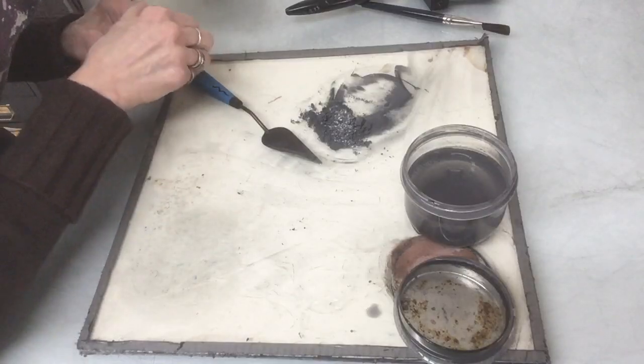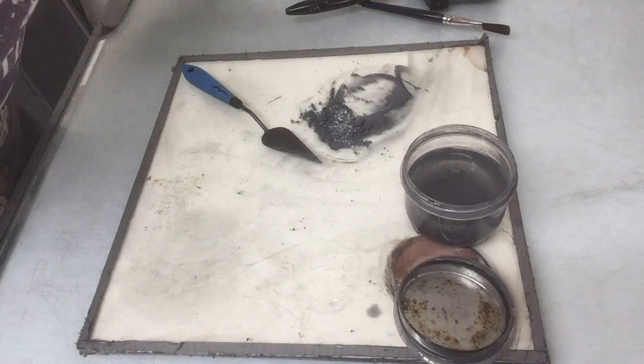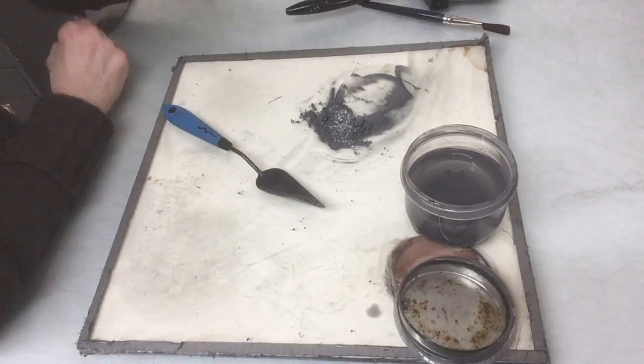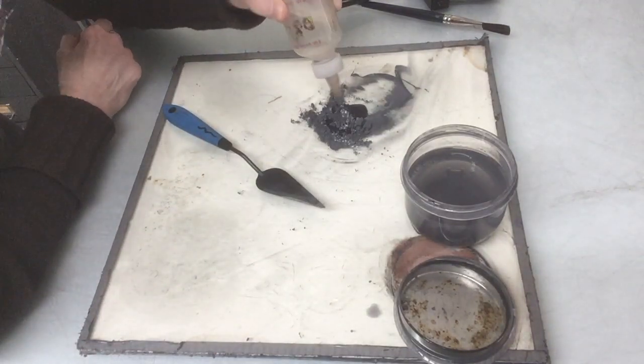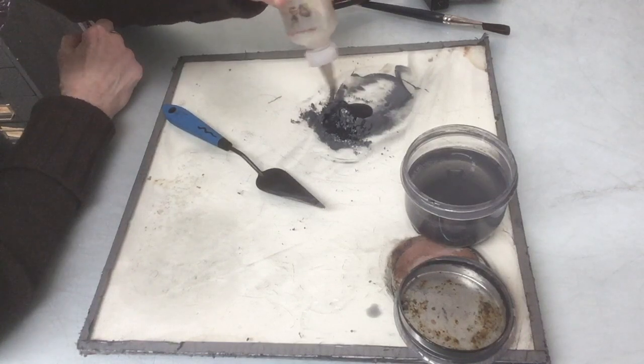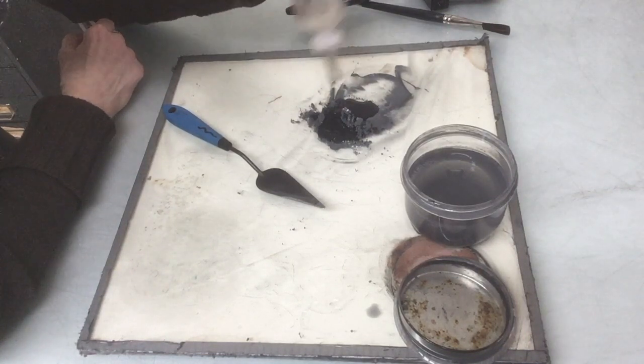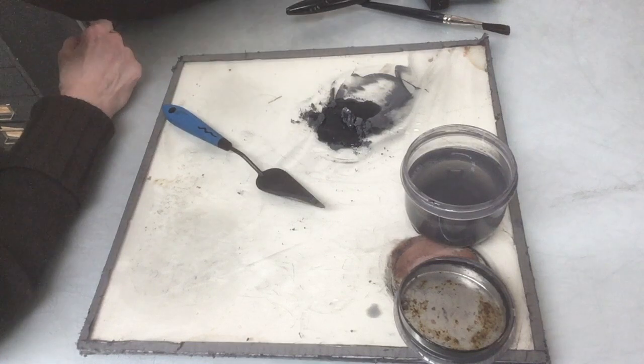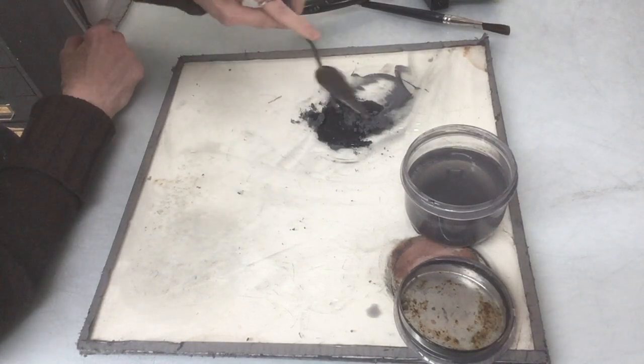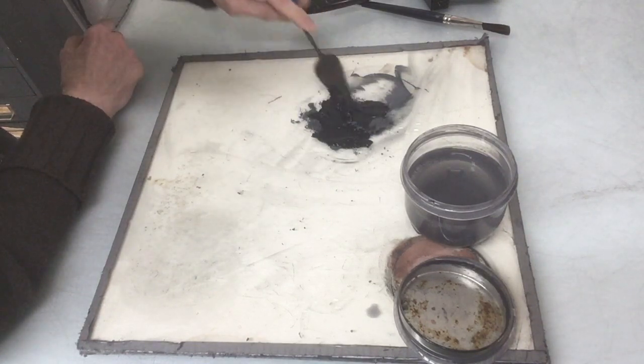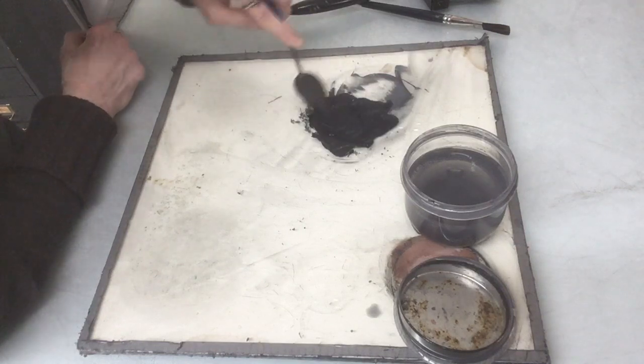If you add too much, it'll crackle and crizzle in the kiln. If you don't add enough, it won't stick to the glass very well, and when you're brushing out the mat, it'll just all disappear. This is water, and this is a palette knife. Mix it up real good.